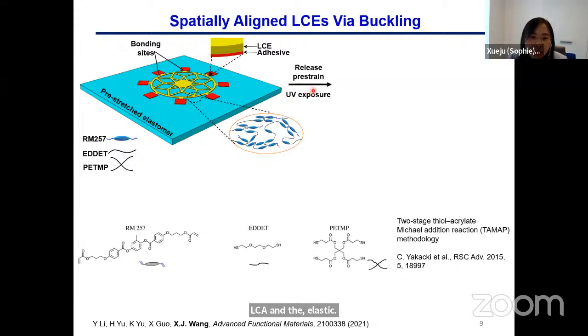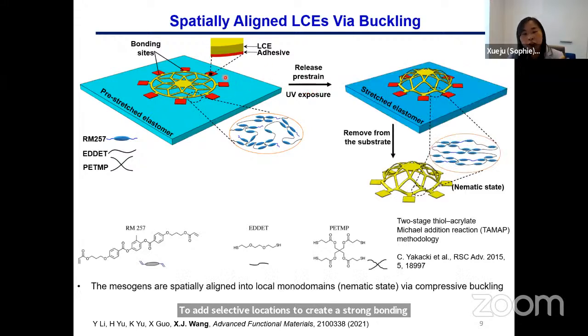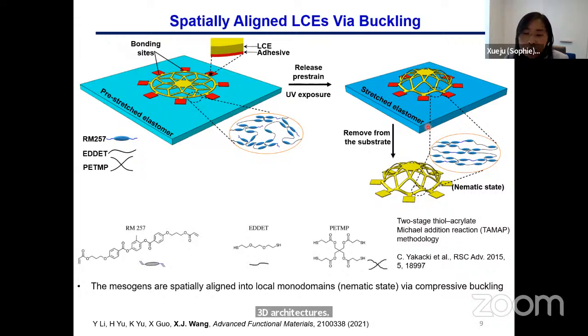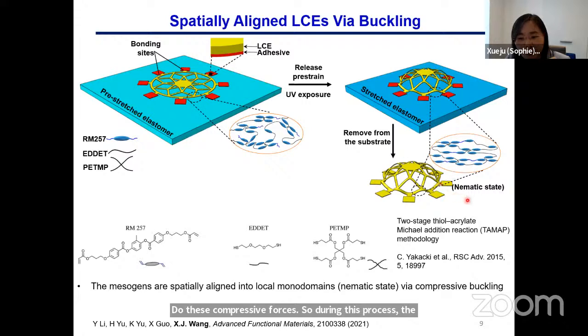And then by releasing the prestrain, we can geometrically transform the 2D patterns into the 3D architectures due to these compressive forces. So during this process, the mesogens are spatially aligned into their nematic state because of the compressive strain in the material. So UV exposure induced additional cross-linking and also permanently programmed the mesogen alignment, which provides immediate access to freestanding 3D LCE structures.